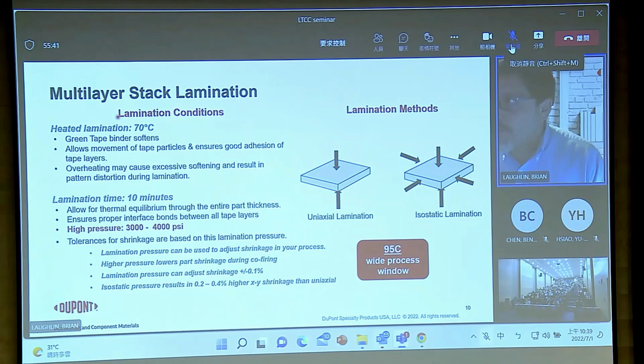And so we put a dot on the sheets for what direction the tape was cast at. But because you get it in the green state, and there is somewhat of an amount of resin left, you laminate at about 70 C, which is above the Tg of the resin. That allows there to be a little bit of plastic flow and some tacking of the layers to each other in a relatively high lamination step, so 3,000 to 4,000 PSI.